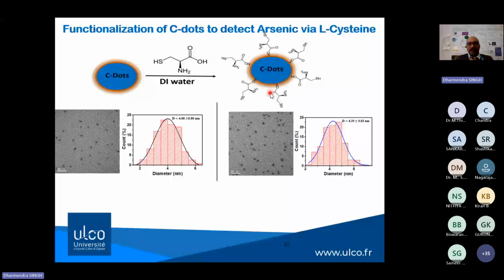We characterized this functionalization by different techniques. First, by TEM, because TEM is one of the suitable techniques to determine the effective diameter of these nanomaterials, whose size is in the nanometer order. In the nanometer order, quantum confinement effects take place, so when you change the size, the electronic and optical properties change. When you functionalize these carbon dots, the effective radius will increase.